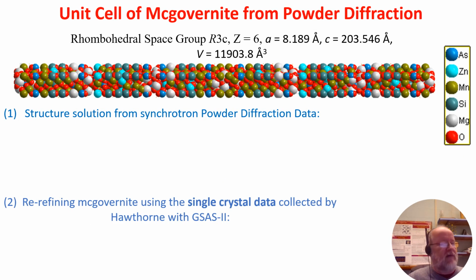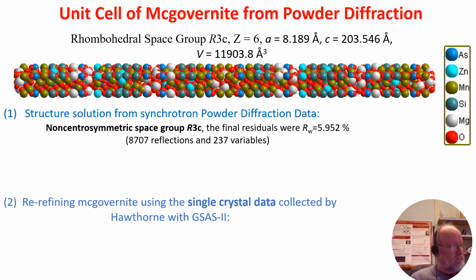Now, there is the crystal structure that we determined. That's the whole unit cell. It consists of 6 asymmetric units. The unit cell itself is 8.189 angstroms by 203.546 angstroms. And in each asymmetric unit, there are 75 unique atomic sites. We put this into Rietveld analysis to refine it down. It converged with a weighted R of 5.952%.